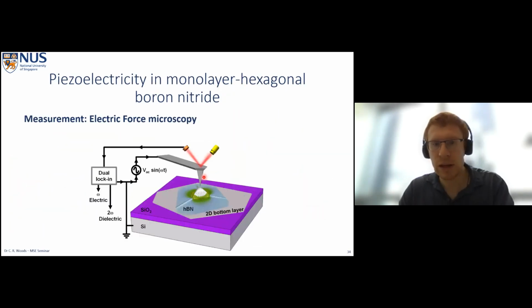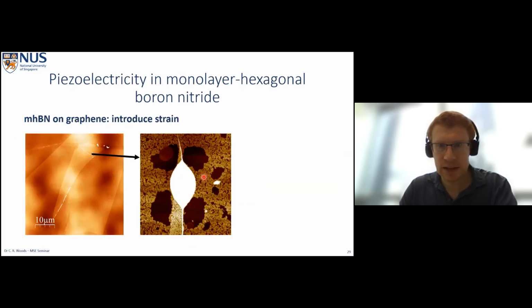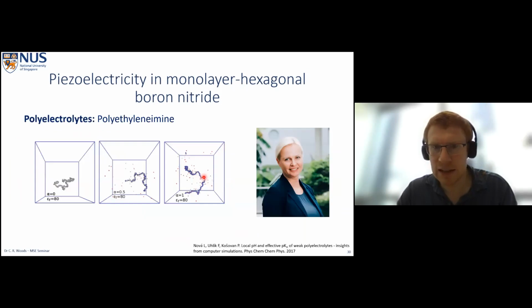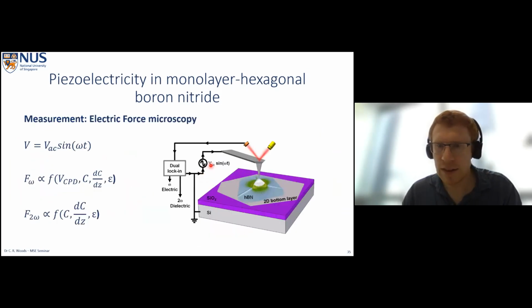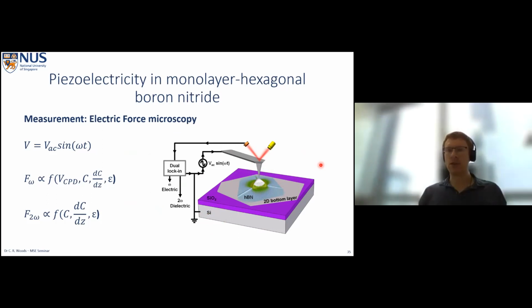One of the reasons why, let's keep going back. So we had this contamination here, but this is incidental. I don't know whether this sample was just left or maybe just treated in a particular way, but we ended up with contamination. We see this, but all the samples we make from then on, we're thinking about how can we decouple our EFM measurement from any topography signals. And so this is why we don't contact the graphene itself, but we contact the silicon, because then we don't have to do any fabrication techniques. We don't have to use any more polymers on the surface. We don't have to use any wet chemistry or anything like that to create contacts to graphene.